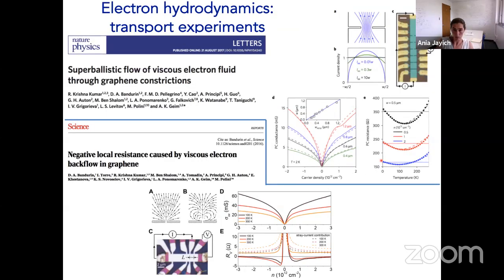And this has been predicted, and there have been a variety of transport experiments that have shown transport signatures that are consistent with electron hydrodynamics. I guess just to summarize shortly, through these measured transport parameters, these experiments infer what the spatial profile of the electron flow paths would look like. So these are examples of two figures. Of course, this flow profile of electrons flowing through a slit or electrons emanating from a constriction into an open space was not directly measured. So I think it's an interesting direction to use direct imaging techniques to actually directly image this type of hydrodynamics.